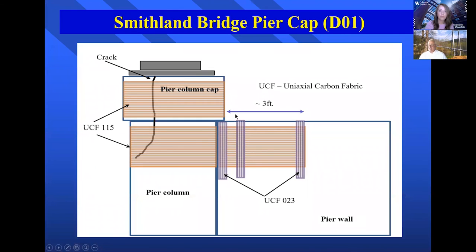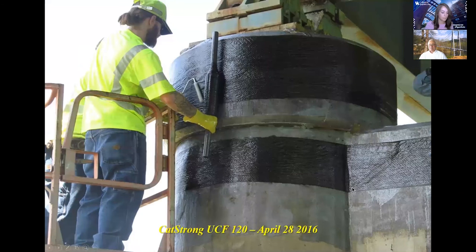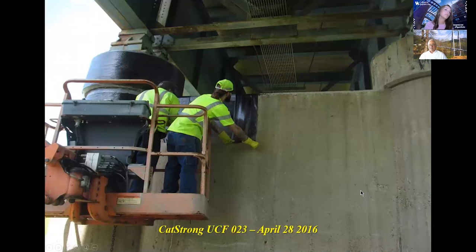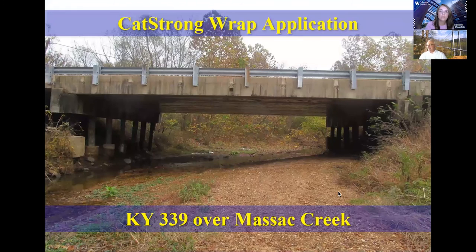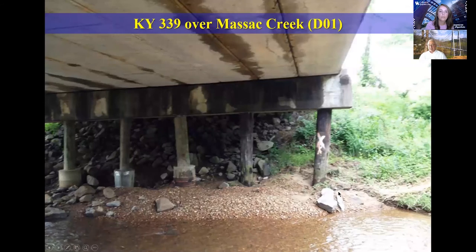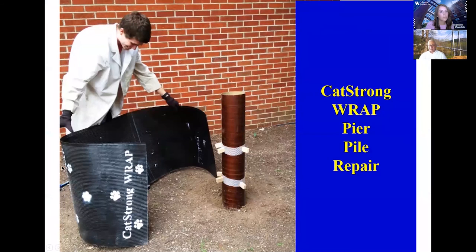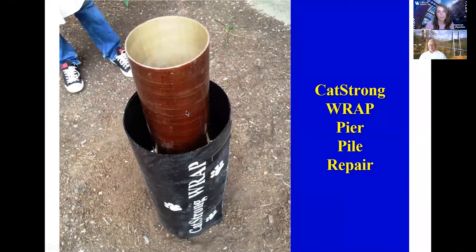So this works, and based on this approach, we've repaired the pier cap in here, as well as the pier itself. And this is the repair. The repair was carried by the district crew. Pile wraps. This is a wrap that we developed in our laboratory. The students actually fabricate them. We call them CatStrong wraps. If this is a pier, we put some spacers around it, wrap it, and fill it with concrete or resin.